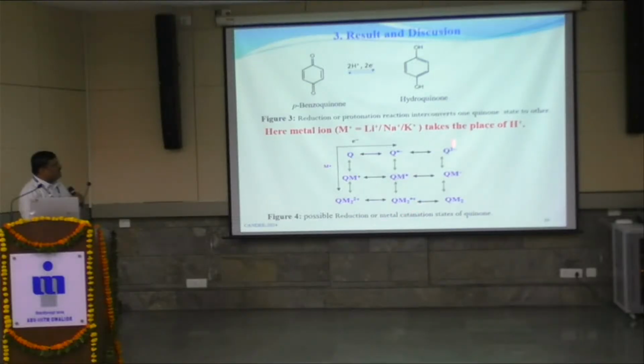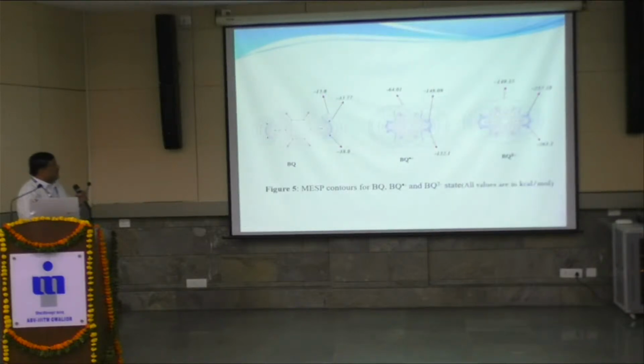And these are the various oxidation and reduction states of the quinone after addition of metal and electrons. First, this MESP calculation shows the charge present on the sp2 hybridized oxygen for the benzoquinone state, benzoquinone radical anion, and benzoquinone dianion. Here the charge goes on increasing from benzoquinone to benzoquinone radical anion and benzoquinone dianion on the oxygen, and all these values are in kilocalories per mole. This state shows the highest negative binding energy.